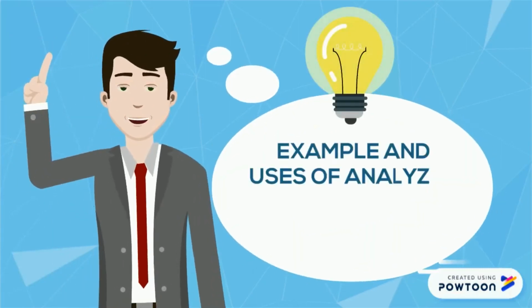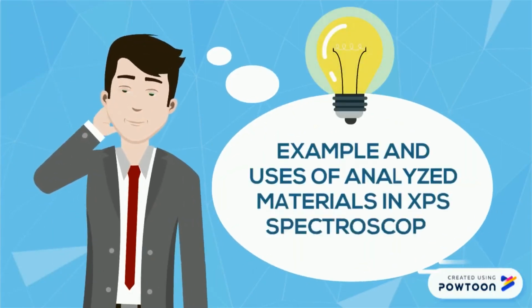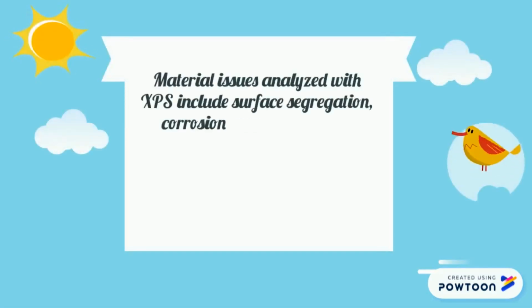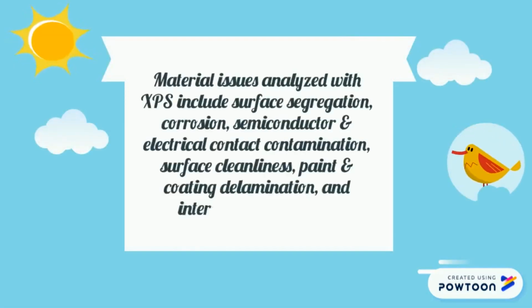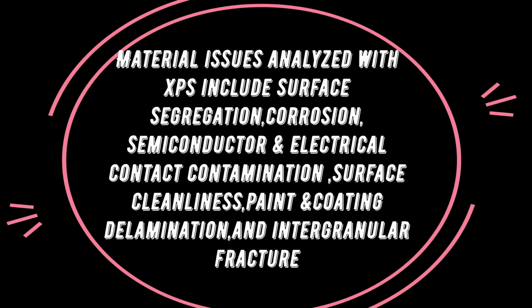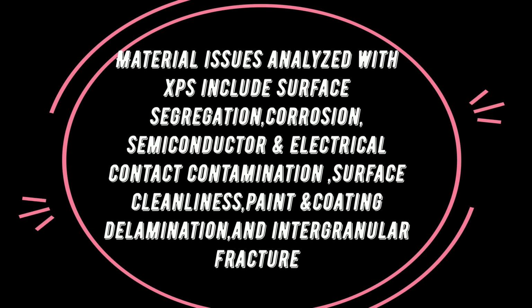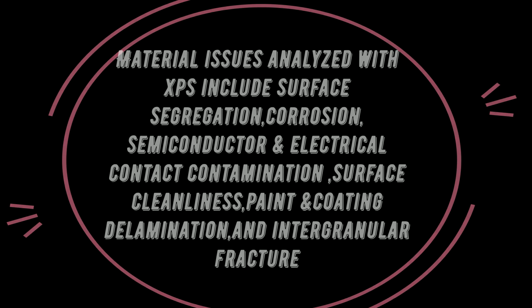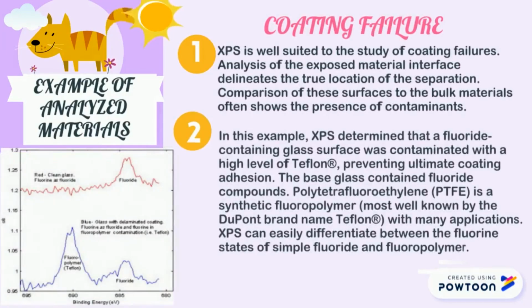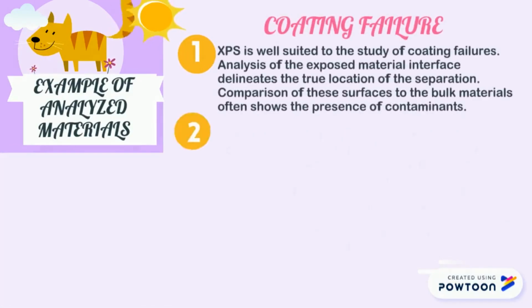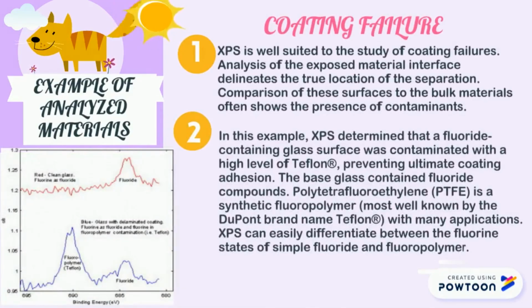Examples and uses of analyzed materials in XPS spectroscopy. Material issues analyzed with XPS include surface segregation, corrosion, semiconductors and electrical contact, contamination, surface cleanliness, paint and coating delamination, and intergranular fracture. Example of analyzed materials: coating failure. XPS is well suited to the study of coating failures. Analysis of the exposed material interface delineates the true location of the separation. Comparison of this surface to the bulk material often shows the presence of contaminants.